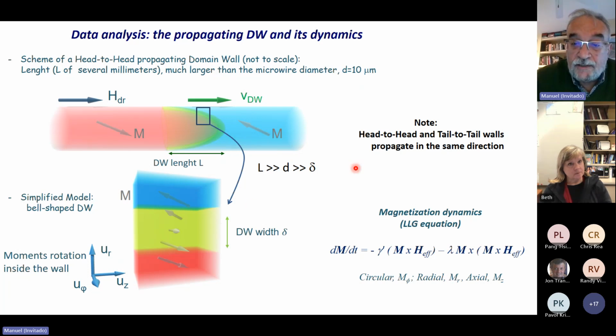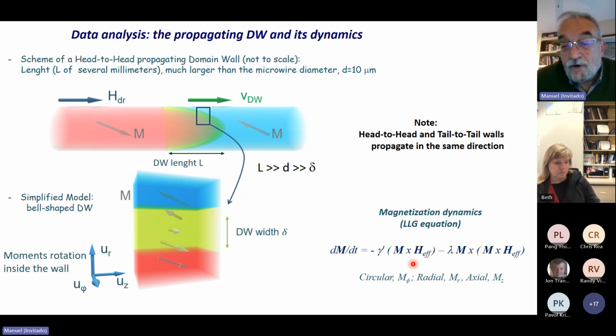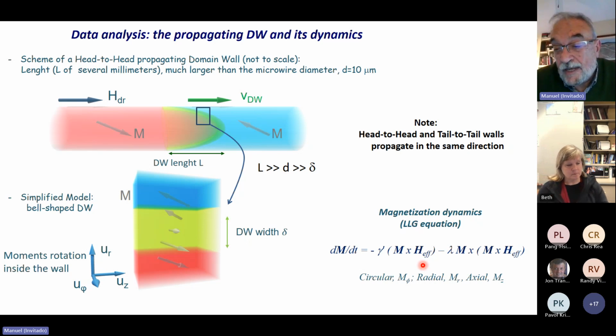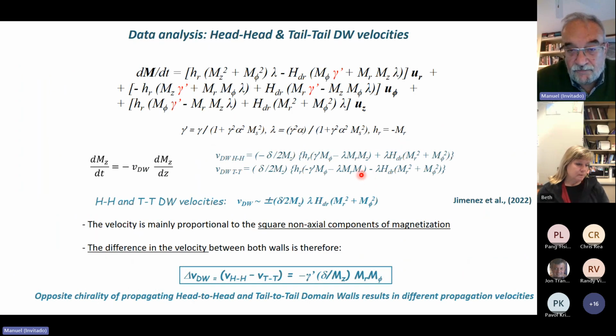So to study the dynamics, we are using the classical Landau-Gilbert equation for the motion of the domain wall that can be head-to-head or tail-to-tail. And this general expression of the Landau-Gilbert equation has to consider the three components of the magnetization, the circular, radial, and axial components inside the domain wall. Well, here are some equations. I skip the interpretation, but just the final outcome. So we find that the domain wall velocity is different depending on whether the wall is head-to-head or tail-to-tail.